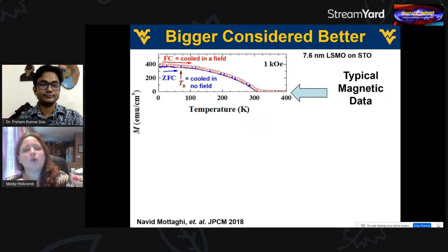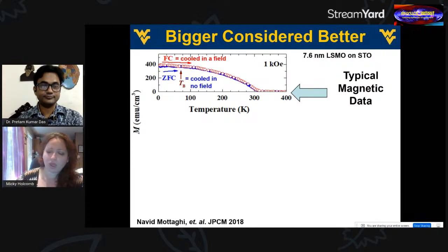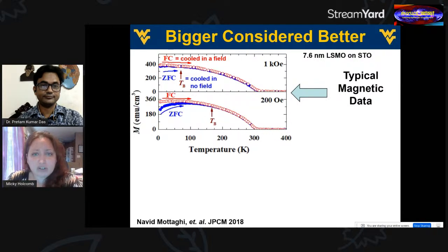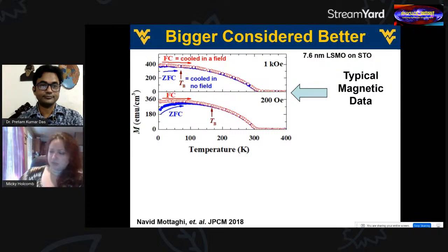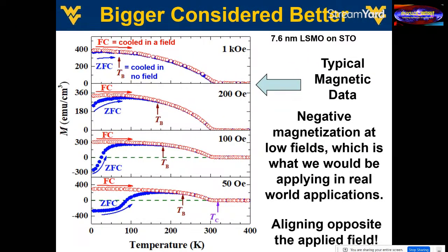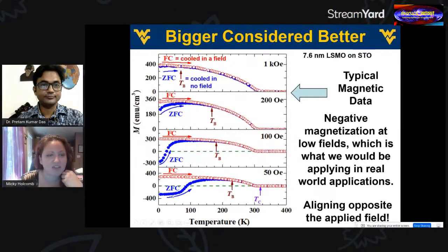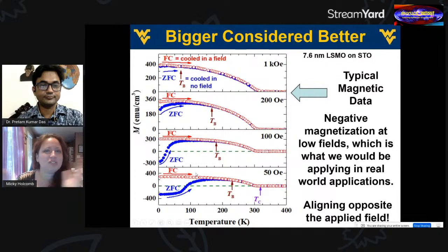I just show the 1,000 Oersted one here so that you can see that when we do our magnetization, whether we cool in a field or not, so that's our zero field cooled versus field cooled, we get very similar measurements. If we drop down our measurement field a little bit to 200 Oersted, a very common thing happens where the zero field cooled starts to drop down a little bit at lower temperatures. But if you go to even lower measurement fields, something really interesting happens. Let's look at the bottom one because it's most dramatic. If we apply a field during cooling, we get almost as strong a signal as we would get in 1,000 Oersted.